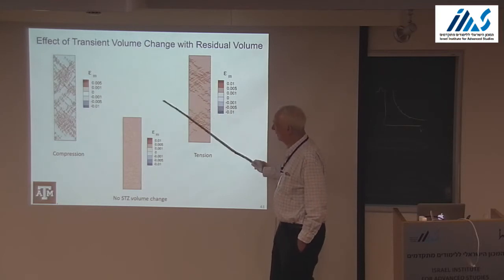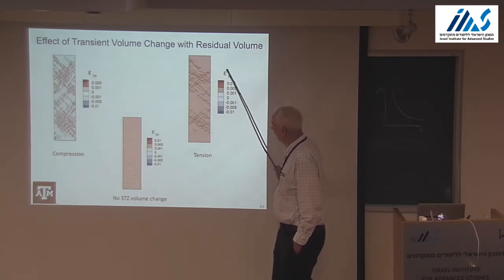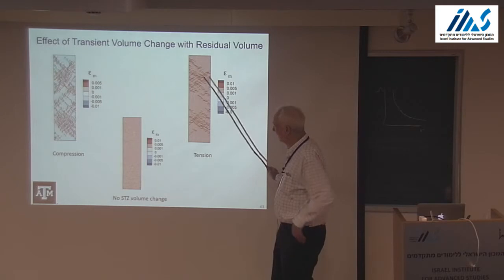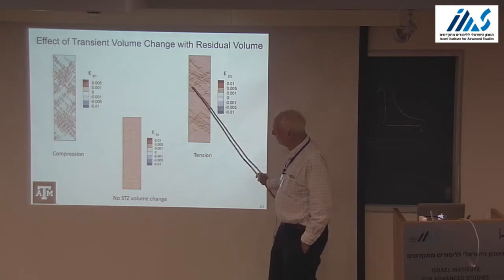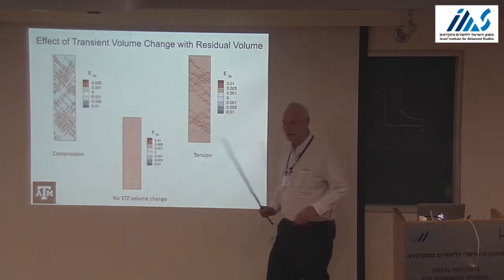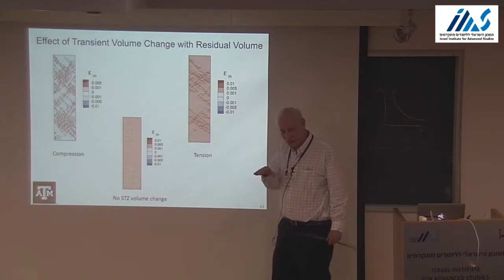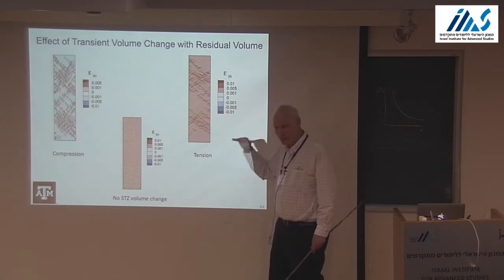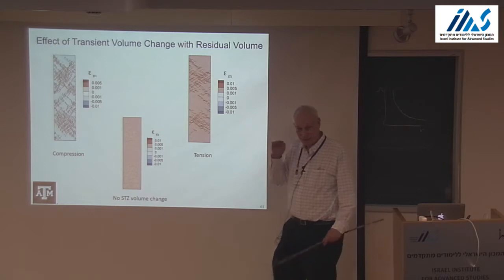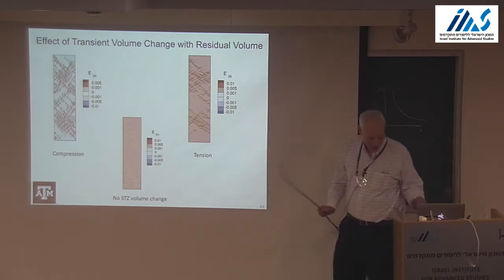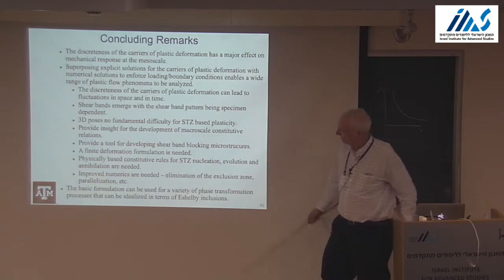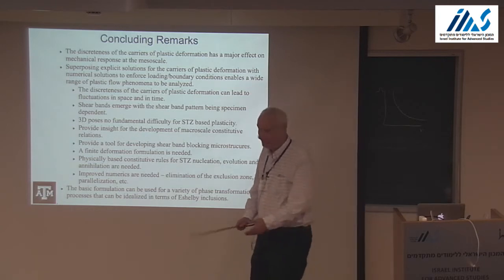One thing that's different, compression, tension, no volume change at all. This is just the residual mean volume change. And you see here, tension and compression give, although the stress strain curves aren't very different, tension gives much more localized shear bands than compression. So it's softer in there. And I won't go through there. I'll just make some concluding remarks.